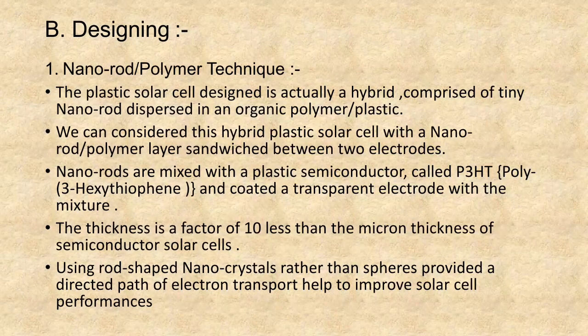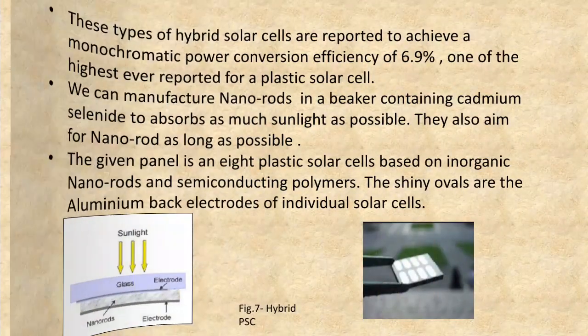The designing of the PSC can be done in two ways. The first one is the nanorod or polymer technique. The plastic solar cell designed is actually a hybrid comprised of tiny nanorods dispersed in an organic polymer. We can consider this hybrid plastic solar cell as a nanorod or polymer layer sandwiched between the two electrodes. Nanorods are mixed with a plastic semiconductor called poly 3-hexylthiophene and coated on a transparent electrode with the mixture. Using rod shaped nanocrystals rather than spheres provides a direct path for electron transport, which helps to improve the solar cell.